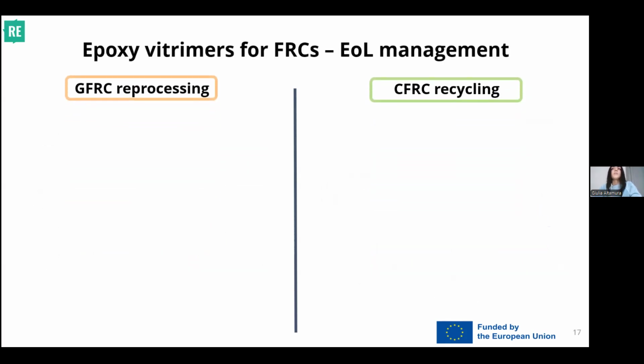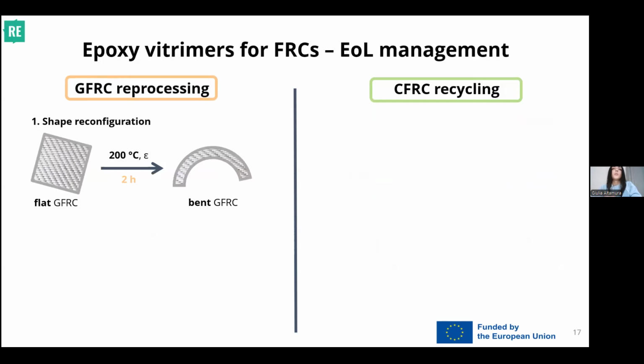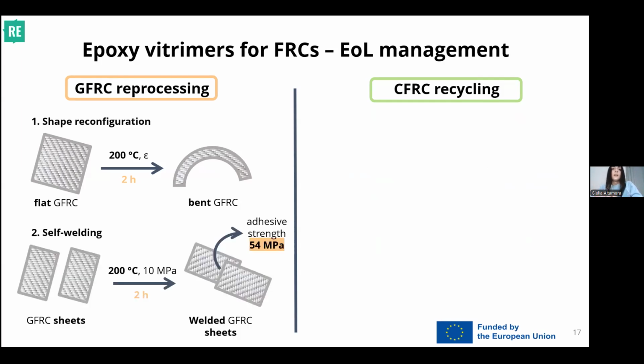Going to the end-of-life management, for the first composite, we decided to reprocess it in 2 different ways. Shape reconfiguration, which means imposing a new permanent shape to our composite by applying a thermomechanical cycle to it, basically a thermosis, in which we repeatedly heat the material at the relaxation temperature for the relaxation time to enable the rearrangement of the macromolecules in the new deformed shape. In the second case, we decided to self-weld 2 different plates of composite together. Again, we heat them up at the relaxation temperature for a time long enough to enable relaxation, and we ended up with this joint with a pretty high adhesive strength of 54 megapascals.